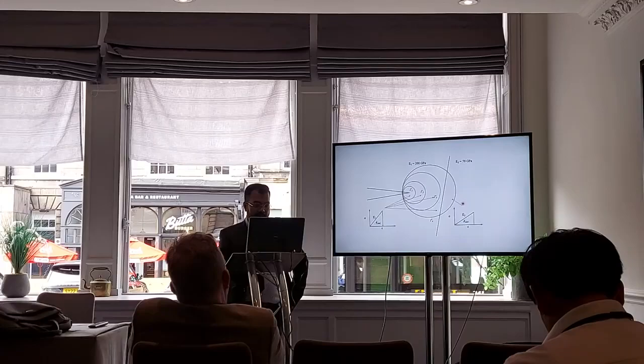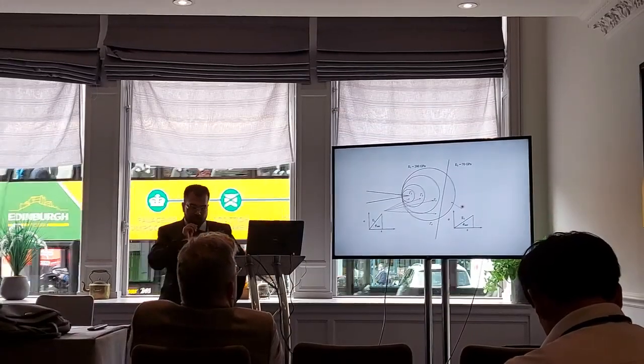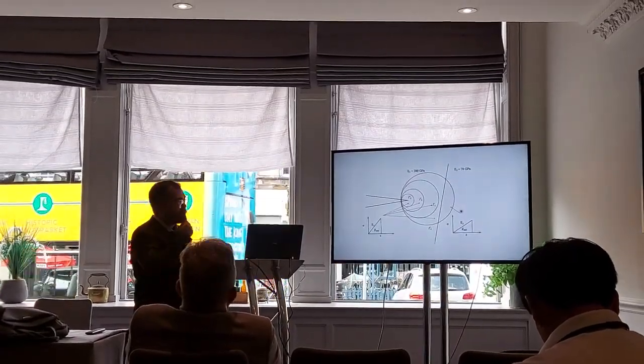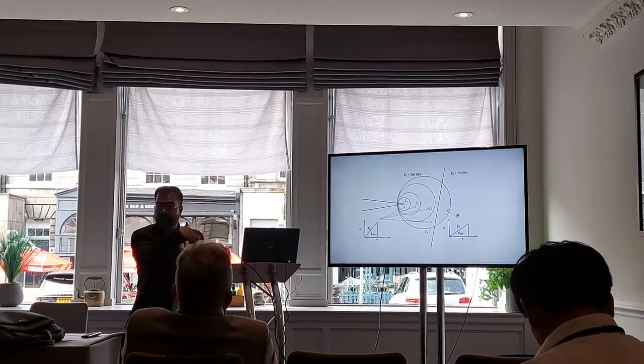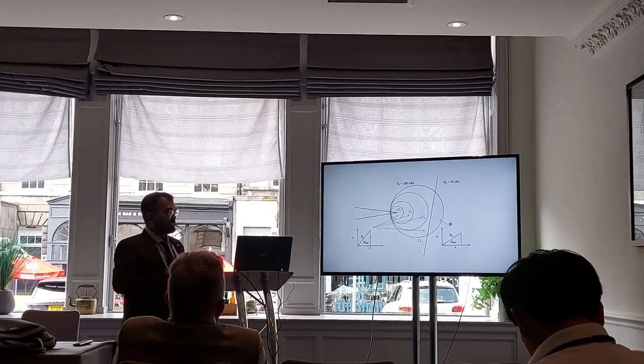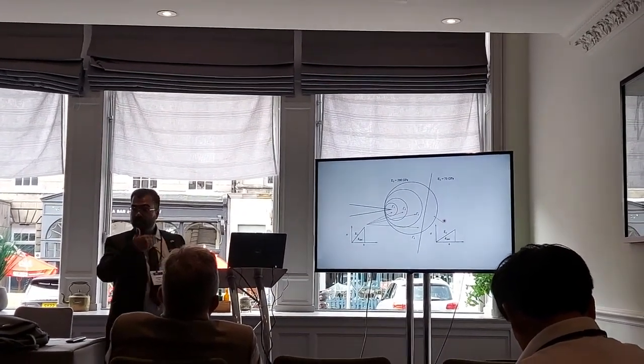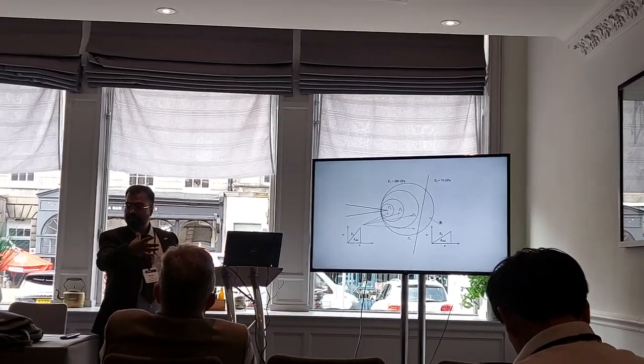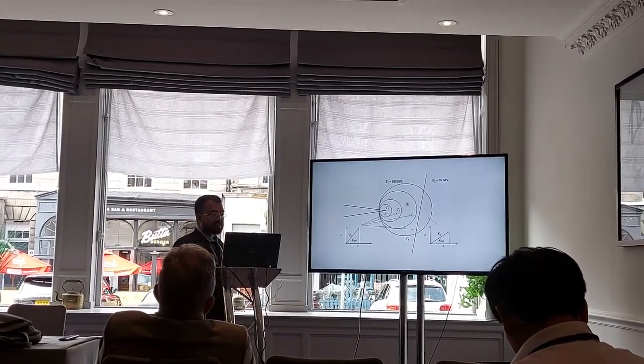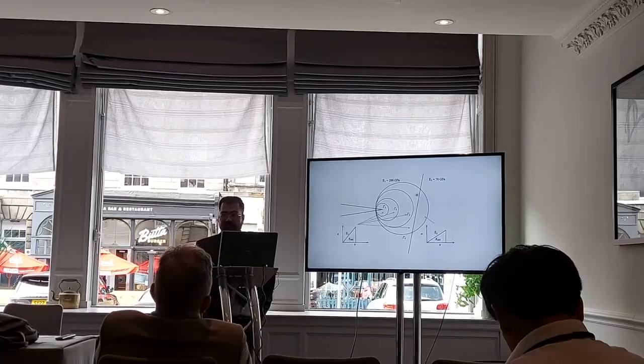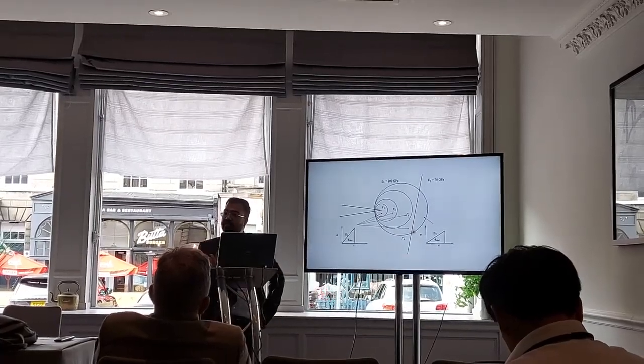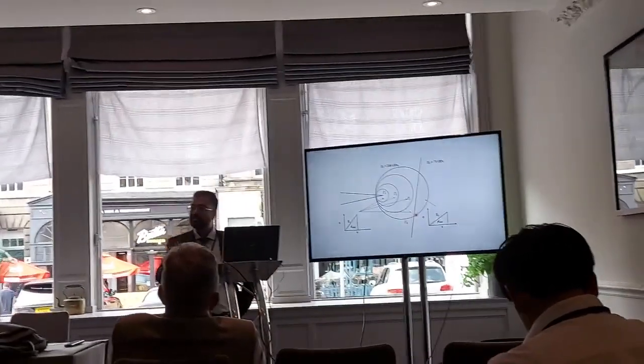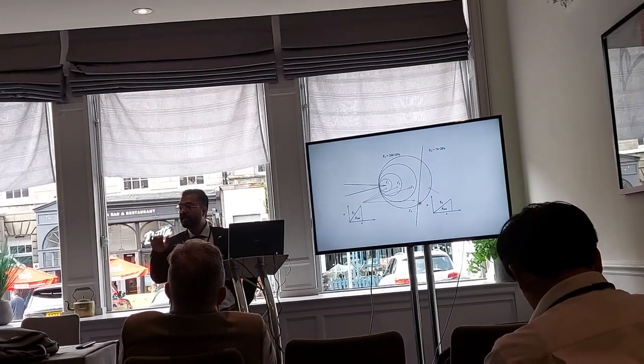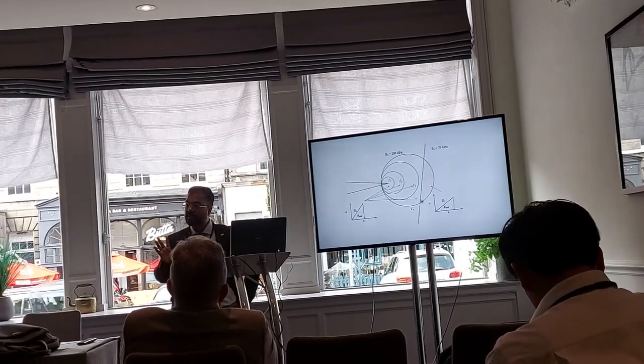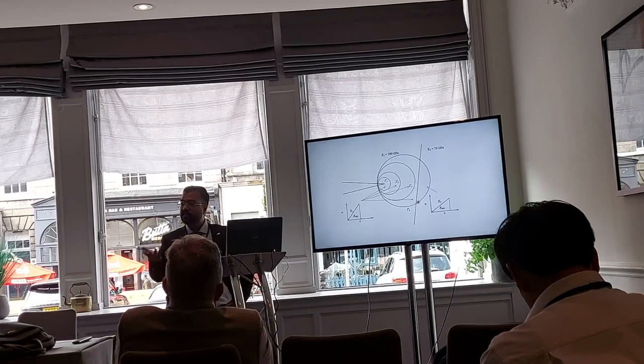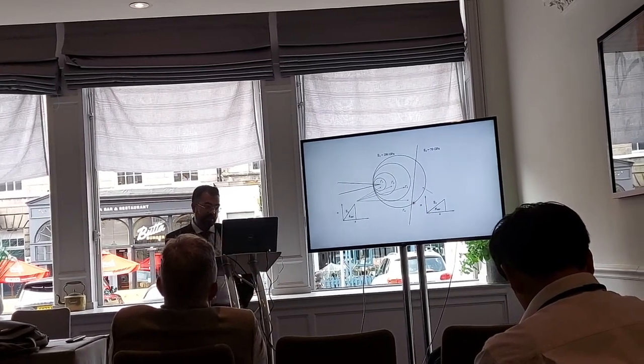This I have explained already. And so what happens here is that you have different contours, gamma 1, gamma 2, gamma 3 at the crack tip. And as the crack moves, the contour will also move. Okay? So suppose this interface was not there, and this was a homogeneous material and everything was deforming following the same stress strain curve. So you will have the same strain energy density in all the contours. So if you calculate the line integral, it will be the same, so it will be path independent.